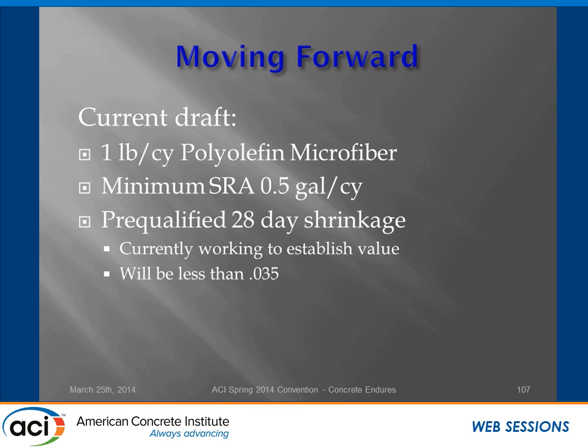So here's the current draft preview. This is what we'd like to vet. 1 pound per cubic yard of polyolefin microfibers. Just specify it. We would like to put a minimum shrinkage reducing admixture in all the concrete, regardless of what 28-day shrinkage you're getting. And so a minimum of a half a gallon per cubic yard, and a pre-qualified 28-day shrinkage value, and we expect that will be less than 0.035.